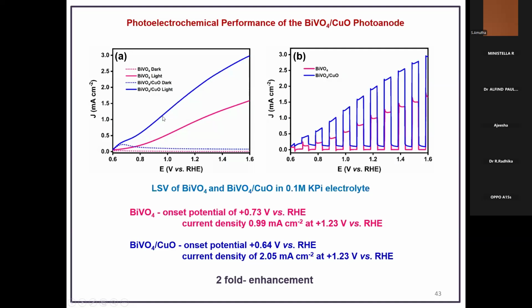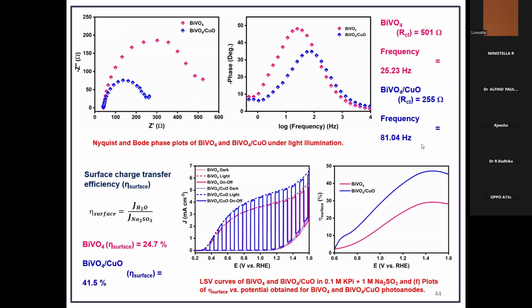Then we have checked the charge separation capacity. For that we chopped the illumination and recorded this particular linear sweep voltammogram. The rise and the fall in the photocurrent is highly stable and reproducible. Then we have also studied the surface charge transfer efficiency using a sacrificial agent, and it is found that the pristine material shows 25%, and the heterojunction material shows 41.5%.